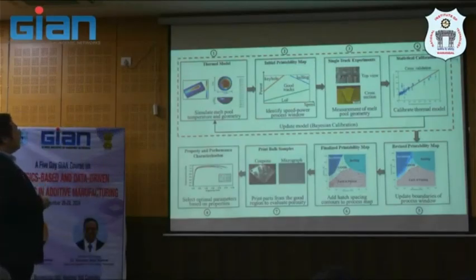From the thermal model, you will see there's some calibration. That means this may be a framework to reduce the defects. So we start from the melt pool geometry, the printability map that we showed previously, and then link to the experiment, statistical calibration. This is a component that we're not talking about very much, but it is important because this information will be used to train the model. So we want to extract some statistics and train it back, and then we hope that we can revise and finalize the process map, and then print something, and hope to improve the performance of the material.